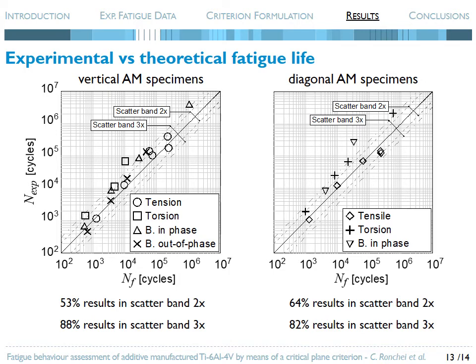In particular, the following remarks can be made. For vertical AM specimens, 53% of the results fall within the scatter band 2x, whereas 88% of the results fall within the scatter band 3x. For diagonal AM specimens, 64% of fatigue life calculations are included into scatter band 2x, whereas 82% of such calculations are included into scatter band 3x. Moreover, when the theoretical results are located outside above scatter bands, they are on the conservative side.